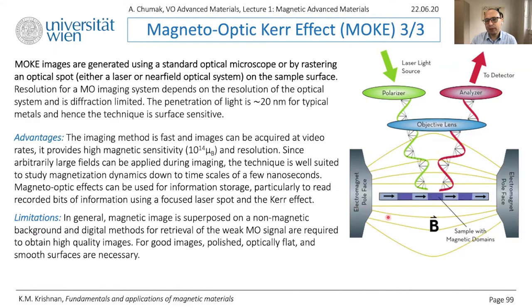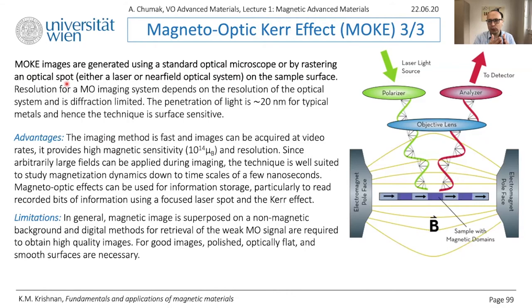Here is a brief sketch of how it looks in the lab. This is your magnetic sample with domains that you want to investigate. Usually you put your sample inside an electromagnet so you can manipulate the structure — saturate it or vice versa. Then you need light: you send it through some lens, it is reflected, and then you send it to a detector where you measure the angle of polarization and ellipticity. MOKE images are generated using a standard optical microscope, focusing on your sample and scanning point by point.